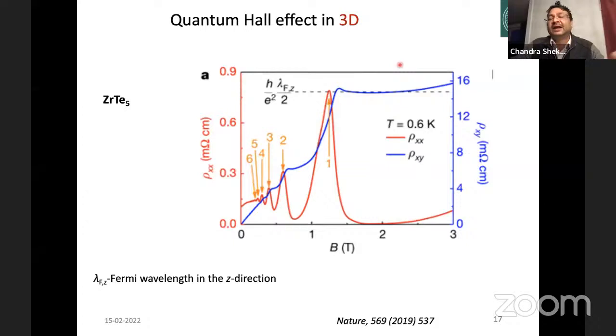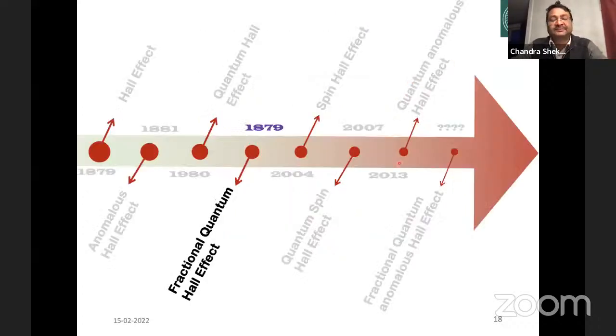We have a linear behavior, like the first observation, where we only see a linear behavior with magnetic field. But when we go to lower and lower temperature, when quantization and this quantum phenomenon occur, we have step-like behavior where we can calculate the value of the step. So it needs low temperature, sometimes high magnetic field, and sometimes special material, to see this quantum Hall phenomenon.